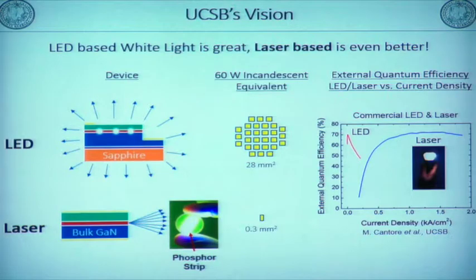So this is the UCSB vision, and you can see the drawing. This is the efficiency of LED as a function of current density. For the LED, the red one, with increasing current density, efficiency drops sharply. So in the case of LED, we cannot increase the current density to get a bright light, because of droop. This is caused by Auger recombination, which is an intrinsic material problem. So we cannot solve this problem.